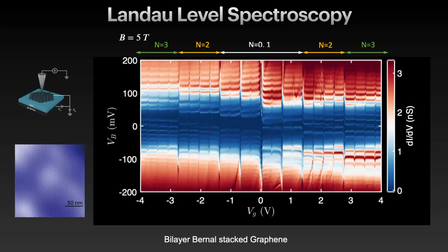But before these experiments that we performed, every time people did STM on graphene or bilayer graphene, doing Landau level spectroscopy, you have to apply a bias to tunnel into a Landau level. All these previous studies showed something that was very reasonable: you apply a bias to your tip, and of course you're going to gate your sample. So essentially all these Landau levels become tilted as you try to probe them, and that made a lot of sense. Except when we started doing experiments, we realized our Landau levels are flat. We're not gating the sample.